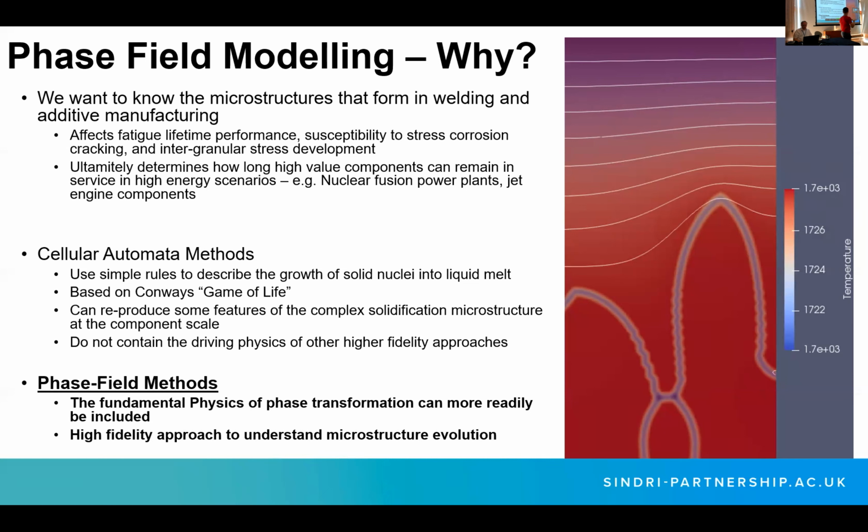So we want to know those crystal structures, because how those grains are oriented, the texture that evolves in the region, how those grain boundaries interact around the weld seam, tells you a lot about the lifetime performance of the components. Most of the work that we do is related to nuclear components, or other high value components where the structure might have to stay in service for decades without the possibility of being repaired. So we really want to understand how it goes into service in a really fundamental way.